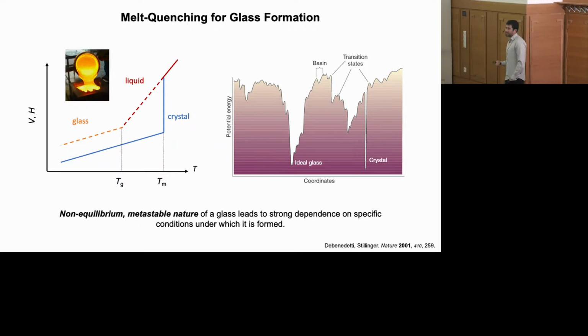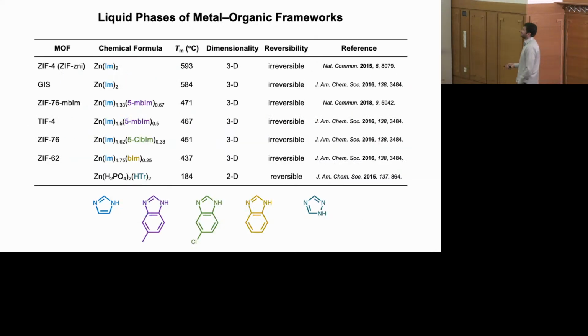And so melt quenching is really one of the most powerful ways of producing a glass. And being able to melt quench and form a glass and to evaluate how different non-equilibrium conditions influence the structure and properties of the resulting glass, of course, requires being able to access a stable liquid phase of a material. And as I mentioned, this is something that's really challenging to do for metal organic frameworks.